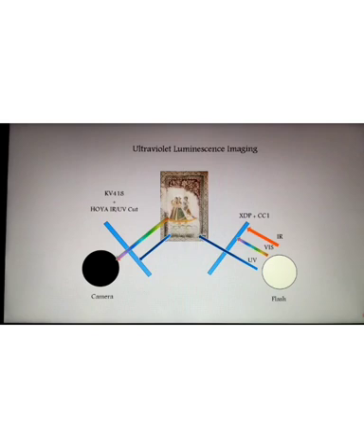The portion of the UV radiation which is absorbed by the material in the painting is converted by the material into the visible spectrum. Thus, a portion of UV light is converted into visible light. On the camera, a UV filter is applied, thus only allowing visible light to pass through it. So when this visible light reaches the camera, it produces an ultraviolet luminescence image.